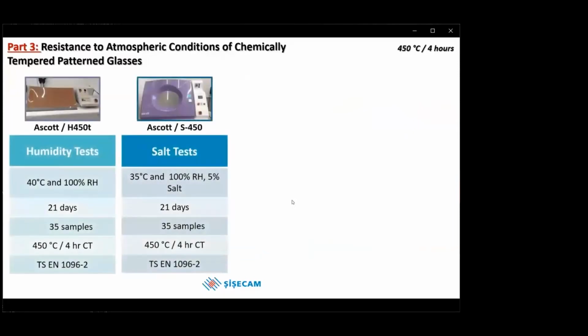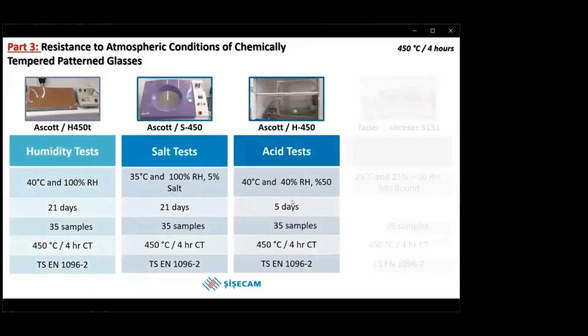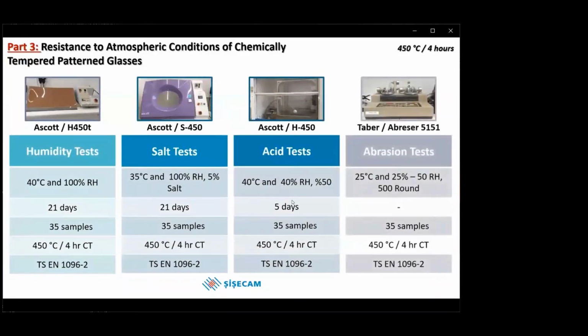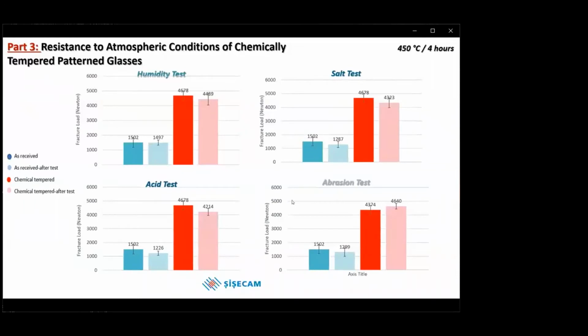Let's continue with the last part. In this part, the resistance of chemically tempered patterned glasses to atmospheric conditions such as humidity, salt, acid, and abrasion was examined. These are our test parameters according to standards. In this slide, ring-on-ring test results values are given. Although a slight decrease was observed in the fracture load values after the atmospheric condition test, it was determined that no significant change was observed because these values were within the standard deviation values.